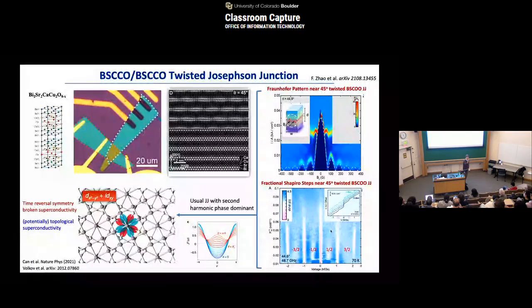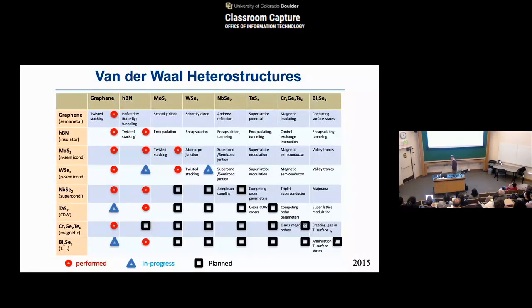So in a sense, the superconductor interface, once you put it at 45 degrees, basically creates time reversal symmetry breaking, potentially spontaneous, of the superconductivity at the interface. And this type of experiment I'm showing you is a way that we can probe that broken time reversal symmetry superconductivity in the interface. So what you see here is basically expanding the system to various things. We start to explore very interesting physics there.